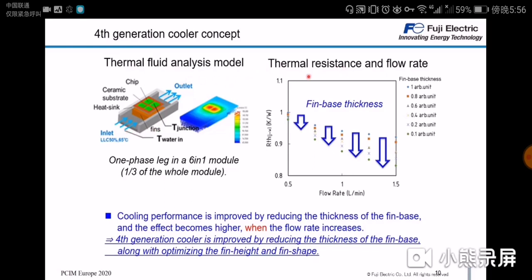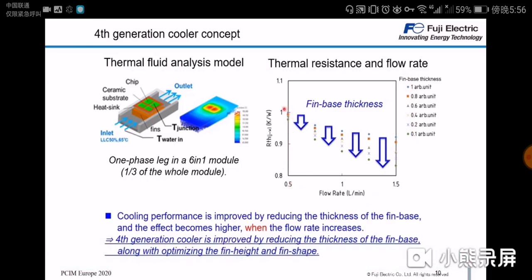On the right side we can see the thermal resistance over the flow rate with different fin base thicknesses. At a relatively low flow rate of only 0.5 liters per minute, you can see that all these points are close together. But if the flow rate increases, then the benefit of this thin fin base thickness is increasing. So at 3 times the flow rate, we have reduced the thermal resistance by quite a bit. And also you can see the effect that the thick fin base shown here on top and the thin fin base shown here at the bottom is becoming much and much bigger. So when we increase the flow rate, the effectiveness of the thin fin base is strongly increased.